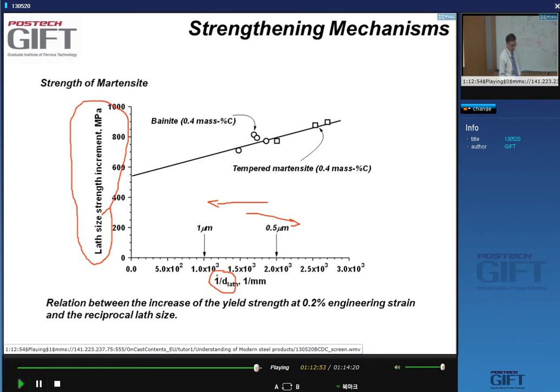Now, what is important here is that most people have reported not a square root dependence on the lath size, but a reciprocal dependence on the lath size. This is probably due to the fact that the normal Hall-Petch relationship breaks down when the grain size, the structural unit size, becomes very small. Because in this case the lath sizes are submicron size, and just like dislocation storage mechanisms break down when you have very small grain sizes, the Hall-Petch equation also breaks down at smaller grain sizes.